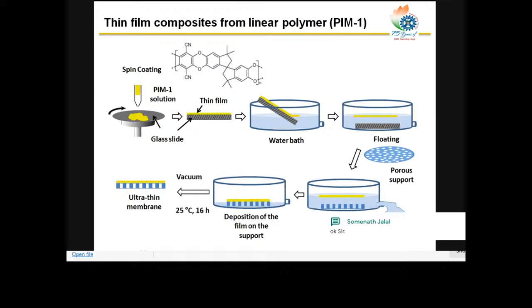With this, we started making a thin film. It was spin coated on a glass slide, and then the thin film was transferred onto a porous support, and finally we got a membrane out of the polymer on a thin porous support. To make a membrane from the polymer thin film, you have to have a porous support. The liquid will go through the thin film and through the support membrane, and you will get the solvent going through the membrane with some rejection property.